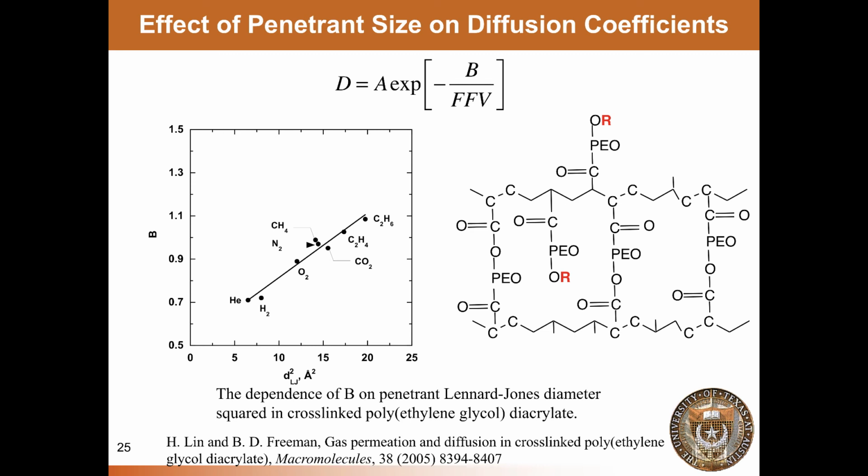That's another byproduct of the transition state theory that we're just talking about. And so within the context of the free volume model, higher values of B are generally associated with larger penetrants in a given polymer that require more volume to open up in order to make a diffusion step. Or alternatively, such molecules are much more sensitive to the free volume and slight changes in free volume than would be small molecules that can get through most any free volume element that might open up.